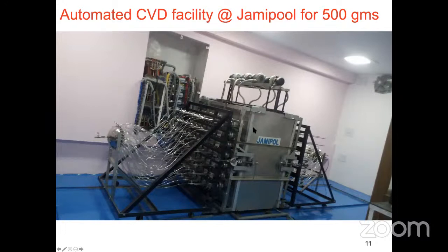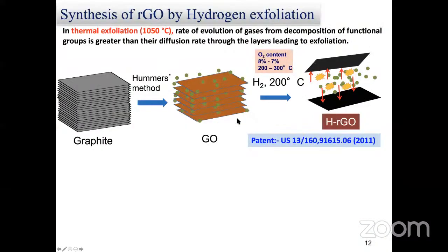So this thing we have actually transferred to Jamipool. So they now have the ability to make almost half a kilogram of carbon nanotubes in a single shot. Once we have done that, we have gone to the two-dimensional graphene. So I have mentioned that this is a graphite. We wanted to get the few layers. We want to peel off few layers.